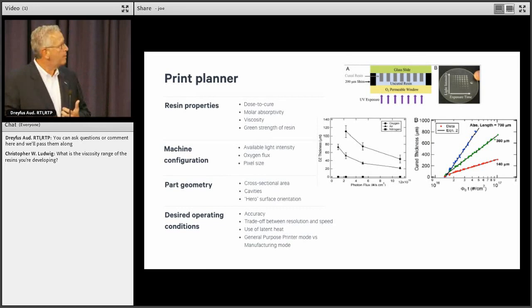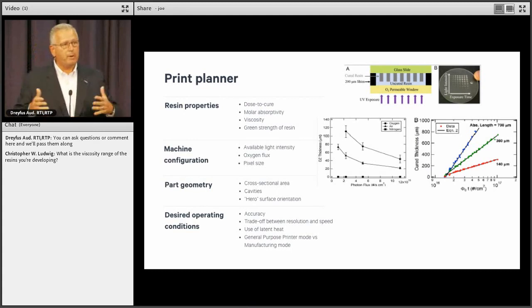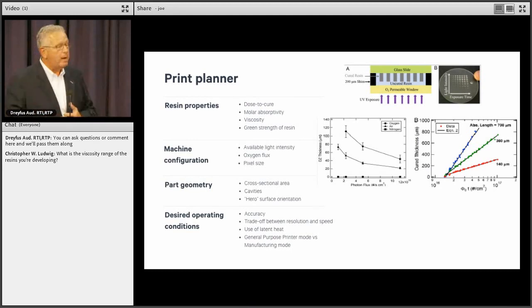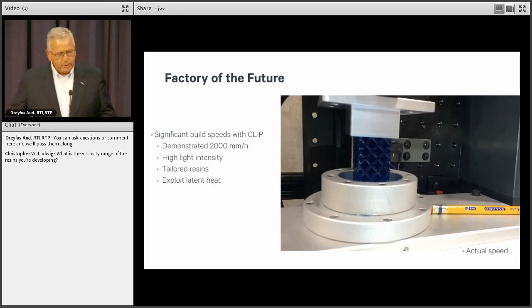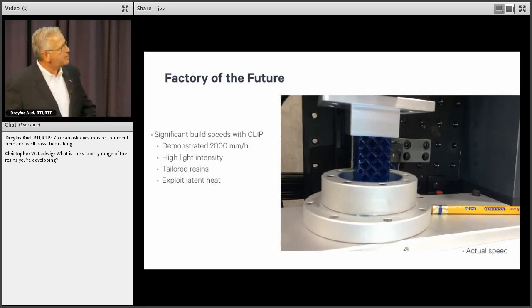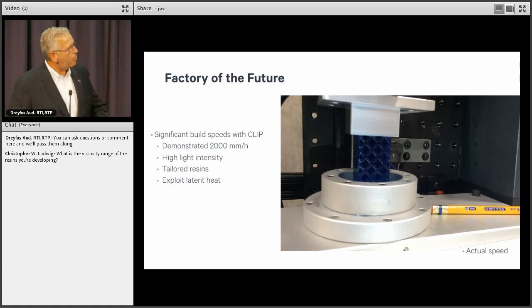Another parameter is the part geometry, because we have to cover different cross sections and the liquid has to flow to the center of the part. So as you change a cross section, that plays a role. If there are any cavities, suction forces can play a role. And if there's a hero surface and you don't want any supports on that particular surface, then there are trade-offs on speed and accuracy.